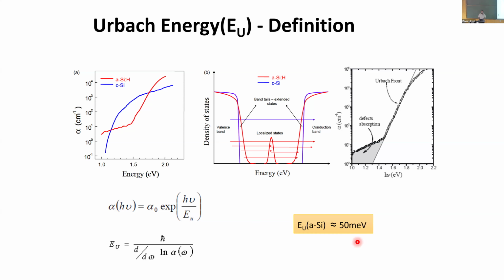So for amorphous silicon, you can quantify it as 50. This is the graph for amorphous silicon. You're essentially looking at these states and assigning a number to it. So for easy reference, if you have higher Urbach energy, you have more defects and disorder. If you have lower Urbach energy, you have less disorder.